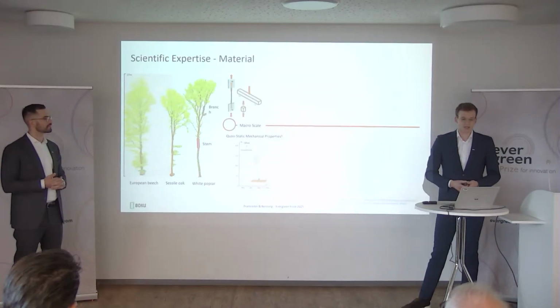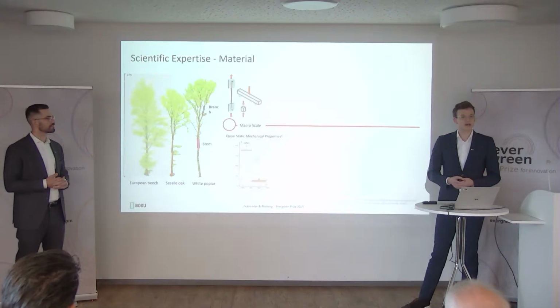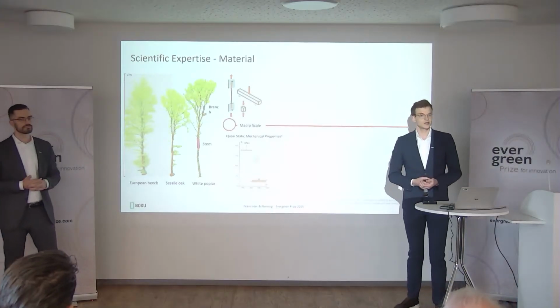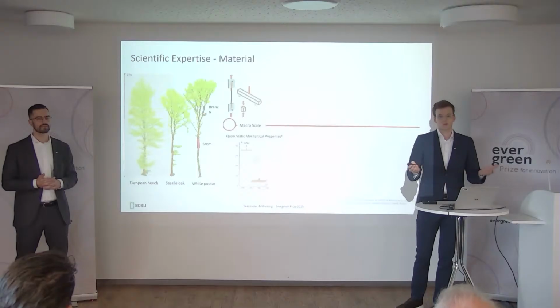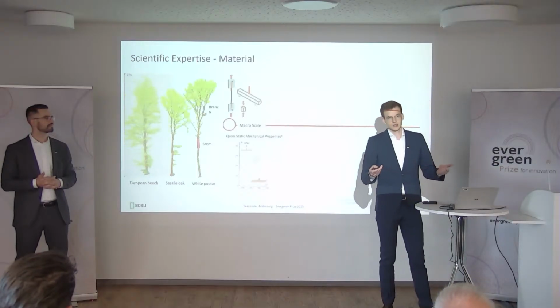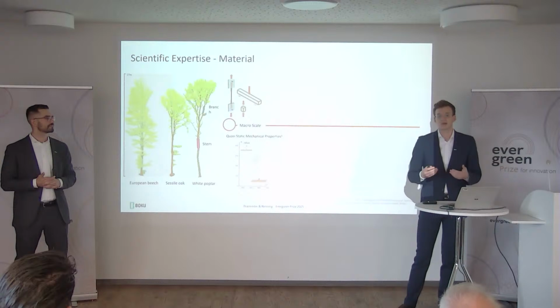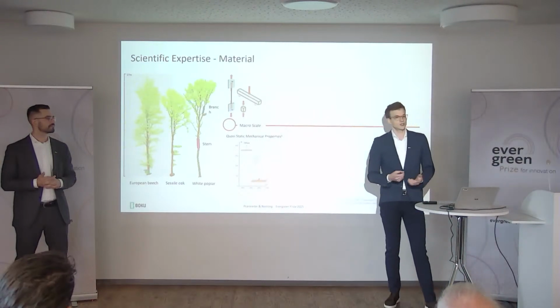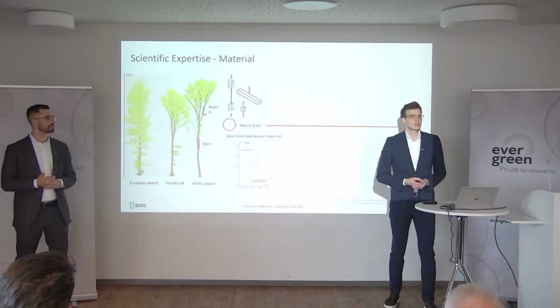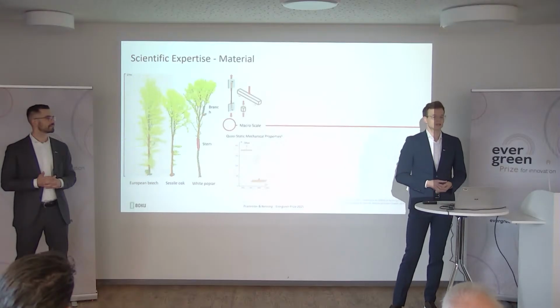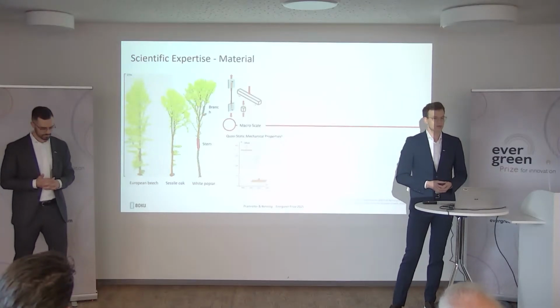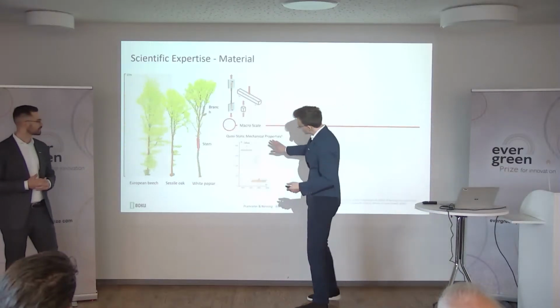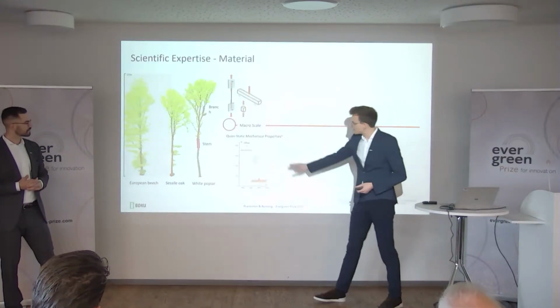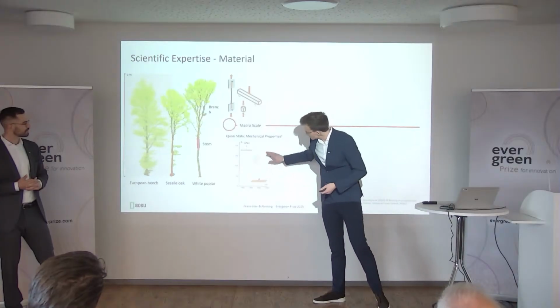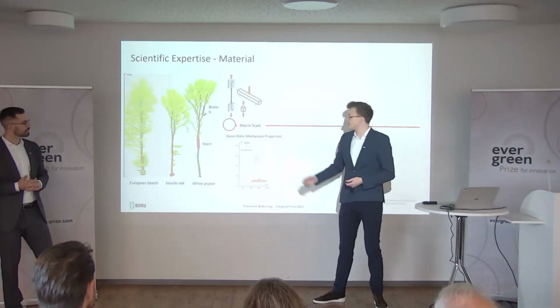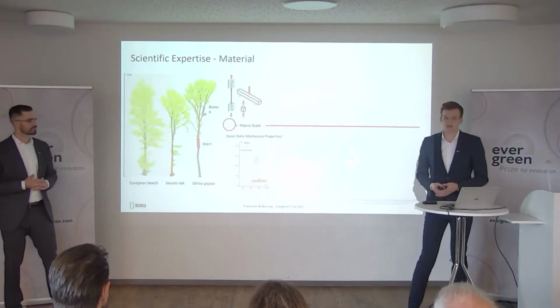And it also made it possible to find out, for example, that branches do have a higher wood density overall for oak and beech. But what do you expect with high wood density? Some would expect higher strength values, but we found out that they are only comparable. For example, for tensile strength, the beech branch was 20% below the corresponding stem wood. But overall, if you look at this material property chart, applied as beams or panels, the orange part is the branches. They definitely can compare with the stem wood, so they do have a technological potential.